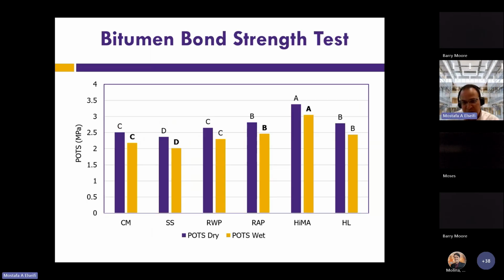In terms of the bitumen bond strength, we found that the highest strength was obtained for the HiMA mix. You can see it here. We have two columns because one of them is the dry and one of them is the wet. The second best performance was the RAP and the hydrated lime in terms of bond strength, followed by the recycled waste plastic and the control mix, and the steel slag was the lowest performer. So again, it's possibly due to the nature of steel slag, which is a slightly different material than the other types, which may affect the adhesion strength between the binder and the aggregate.